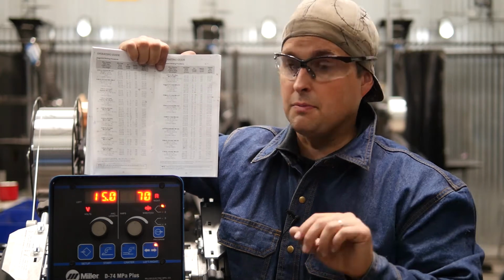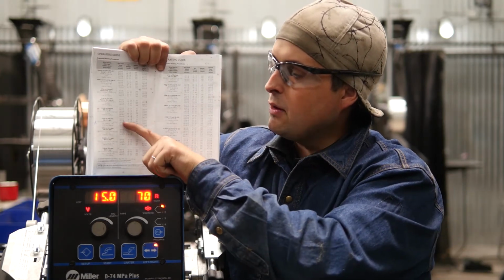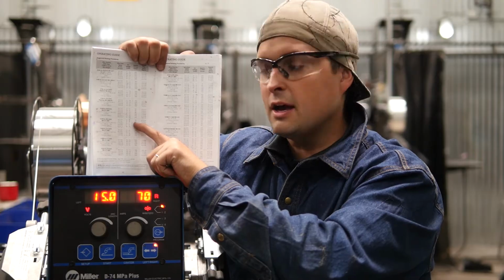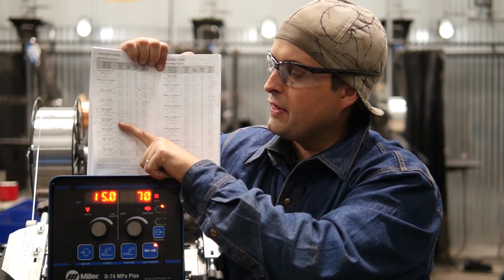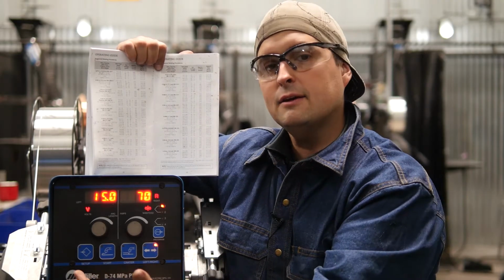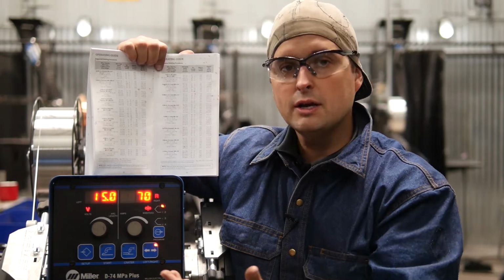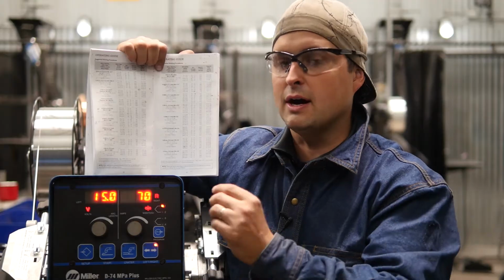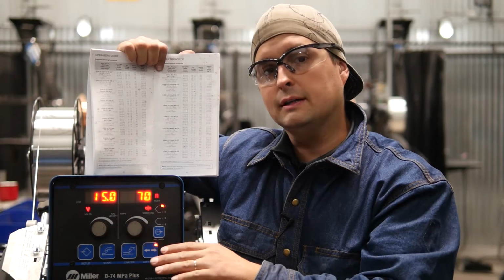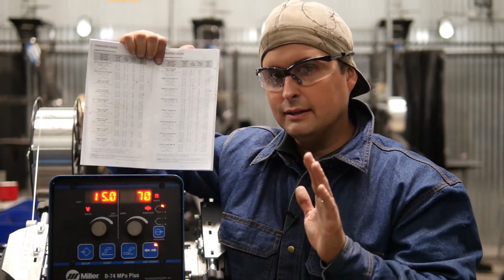Now, we're going to be welding on some thinner material, so I'm going to choose a wire feed speed that's going to produce me a lower amperage. So I'm going to go with 70 inches per minute and 15 volts. We've got a range on our voltage we can use, 15 to 16 volts, but if we remember what voltage does, it lowers our arc length. And I'm trying to get a small little weld out of this, so I'm gonna go with the smaller or the lower voltage.